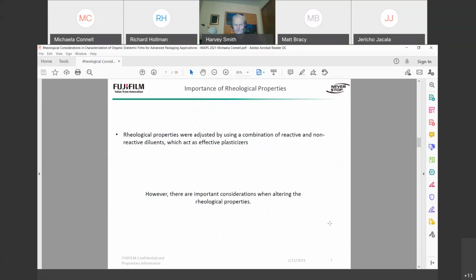So we adjusted the rheological properties of the polyimide dry film by using a combination of reactive and non-reactive diluents, which act as effective plasticizers. When we plasticized the film, we were successful in creating good flow at lower lamination temperatures. However, there are important considerations when altering the rheological properties that also needed to be studied.